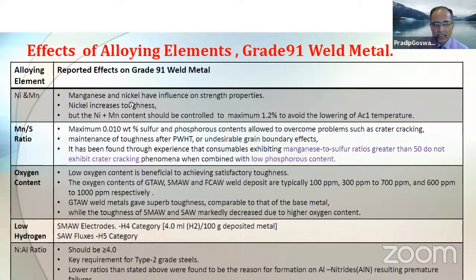Nickel plus manganese. Manganese and nickel have an influence on strength properties. Nickel increases toughness. As you know for sure, it's a very common element where toughness is needed for any alloyed or stainless grade of steels. But with respect to P91 alloys, nickel has a good role to play, but it should be under control. So the code specifies that the nickel plus manganese content should be controlled to a maximum of 1.2% to avoid the lowering of AC1 temperature. AC1 temperature, in fact, is the lower critical temperature.